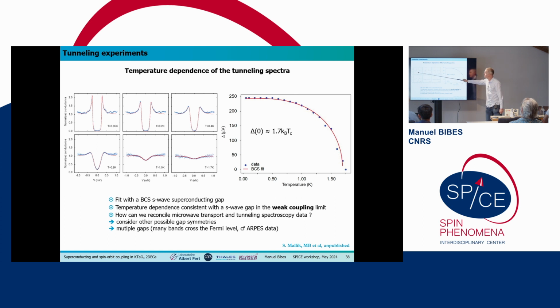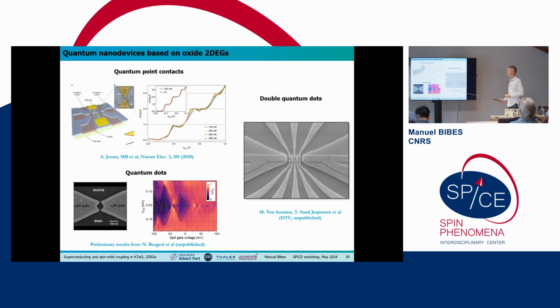If you look in a little bit more detail, as I say, maybe you have 2 gaps, or maybe the symmetry of the gap is a little bit different. Maybe there's some recent paper in Nature Physics with a completely different system that has gap features that look like ours, and the analysis is with a p minus ip order parameter. In fact, as I showed you, we have multiple bands, so perhaps it should be expected that we have different order parameters. So what do we need to be able to do this very nice fancy experiment that you guys were showing yesterday in particular?